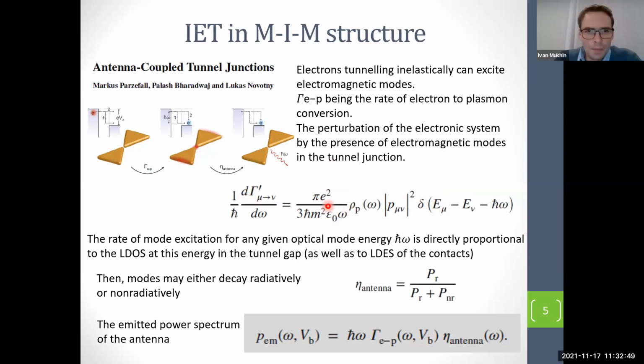So maybe I skip some parts. What is important is that the rate of mode excitation for any given optical mode energy is directly proportional to the local density of states of the system as well as the local density of electron states of the system. So the first process is to excite the local plasmon in the tunnel gap. Then these modes can decay radiatively or non-radiatively.